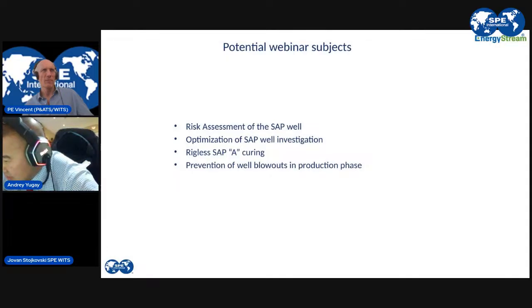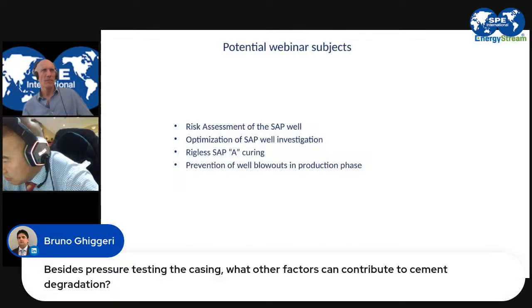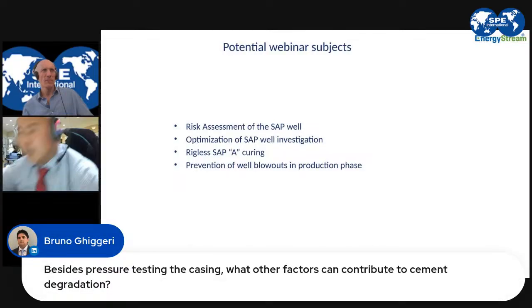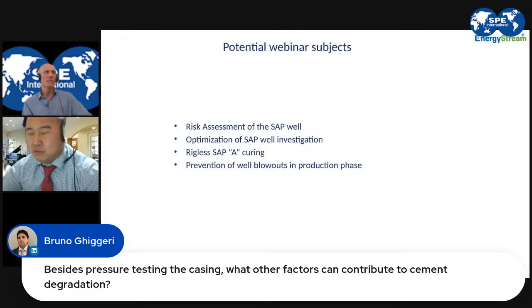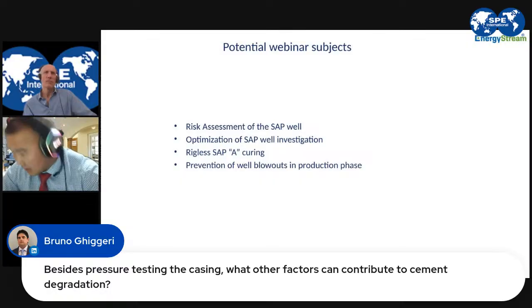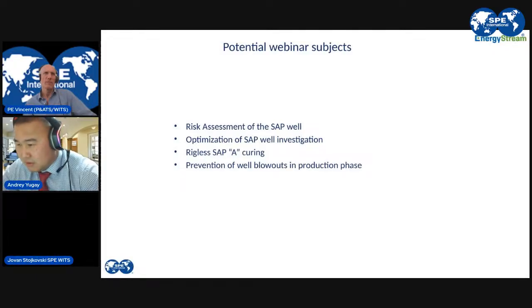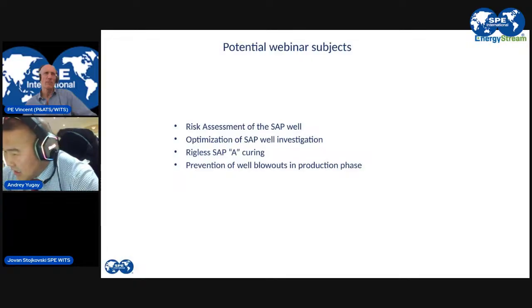Besides pressure testing the casing, what other factors can contribute to cement degradation? Well, it's all about pressure and temperature cycling. But if we're talking about special projects like CO2, yes, if you have CO2, you need to use CO2 resistant cement. If you have high H2S, you need to use H2S resistant cement. But chemical degradation of cement normally doesn't happen in most of the environments in the oil field industry. So it's normally just pressure and temperature cycling.